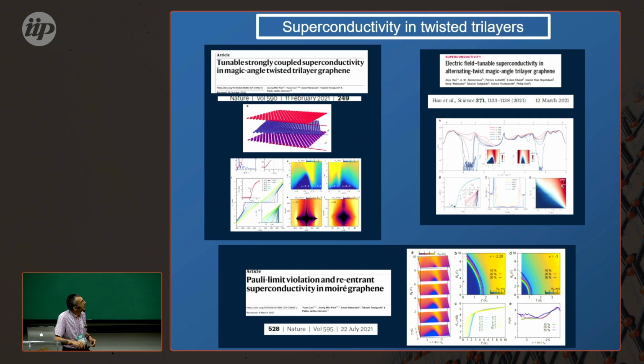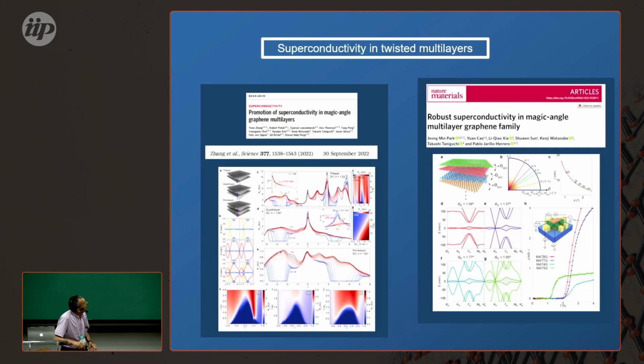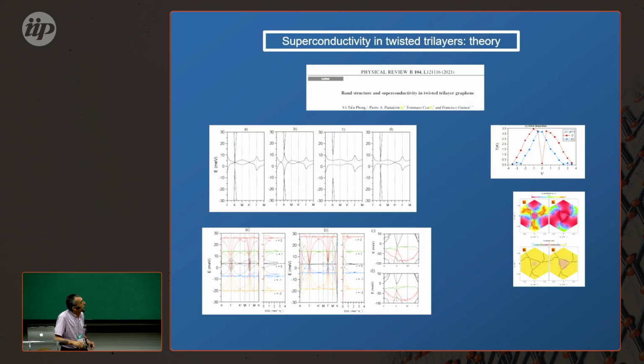As you probably know, twisted trilayers, which can be reduced to symmetric twisted trilayers, were studied next after pioneering work by Han et al., and they found superconductivity, also in higher trilayers. We did calculations and we got basically the same thing—superconductivity in the same range of critical temperature. By the way, the order parameter we found was F-wave again, like in the case of Fu and Crepel.